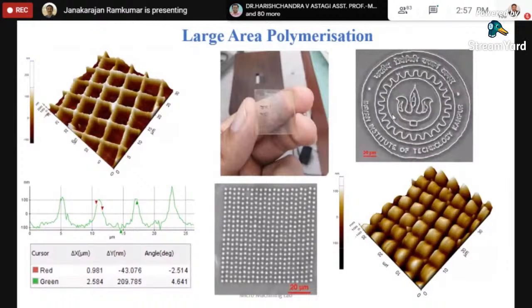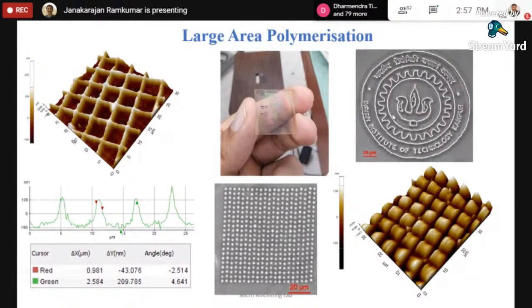If I use a femtosecond laser, then I will be able to get very clear features. But I am developing a low-cost machine using a nanosecond laser, and I am trying to use the pulse, follow the attenuator concept, Nd:YAG 1064, and get the output for polymerization. So if you look at this figure, we have created smoothening of the surface of the dimples, whatever we have made.